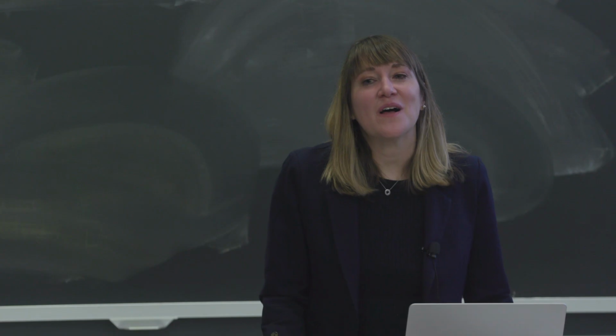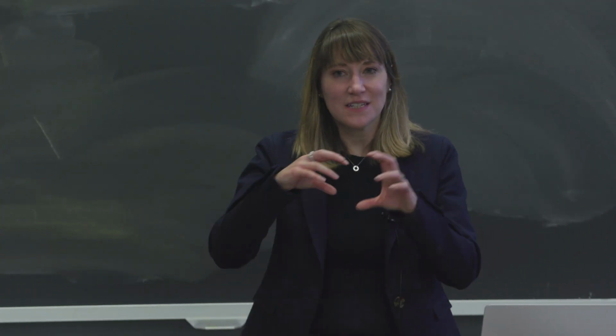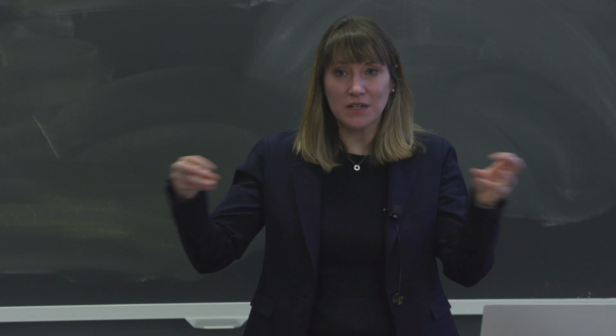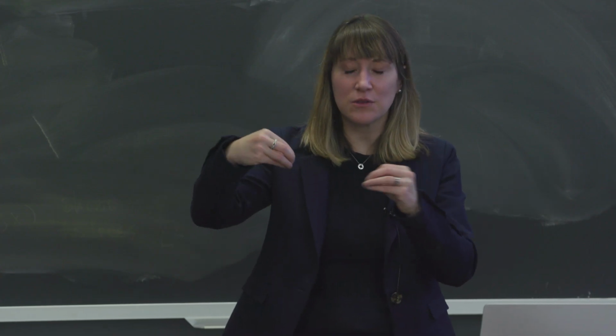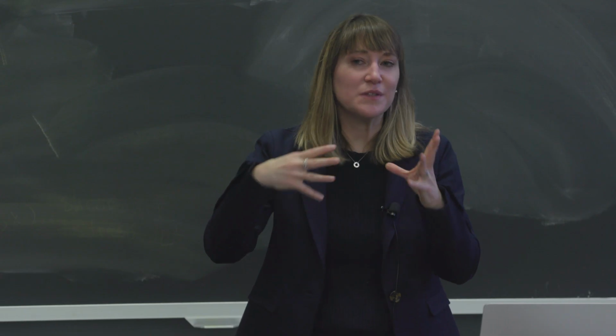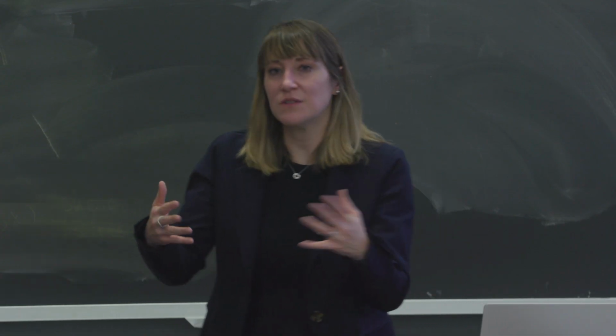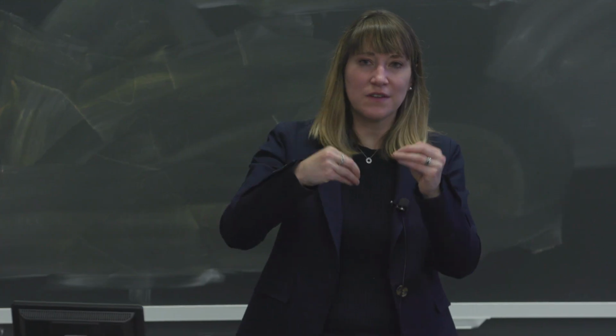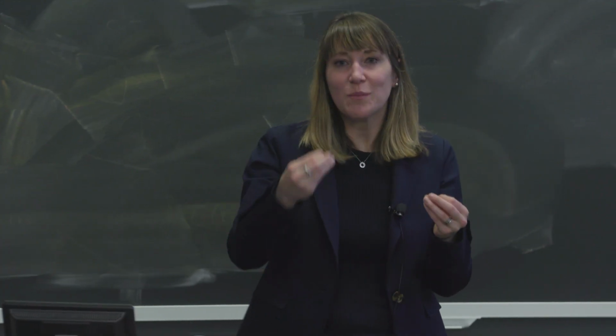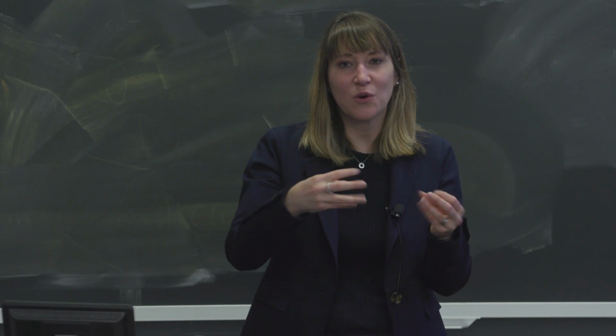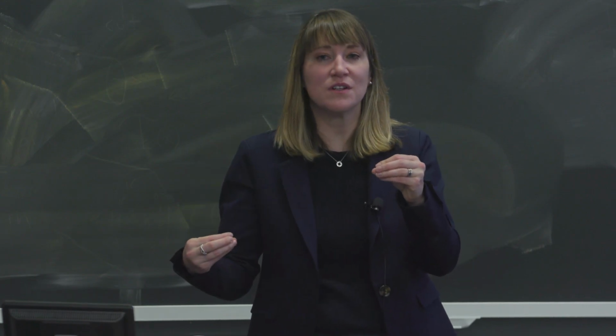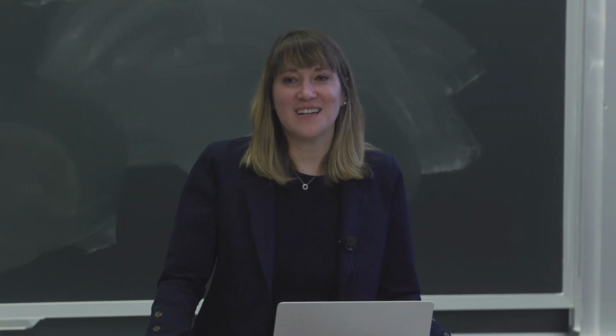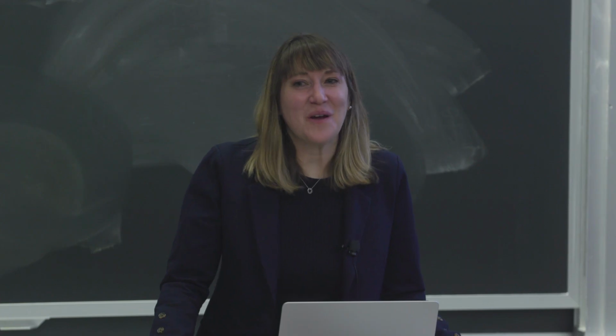Why does it work? I'd love to know. Well, I alluded to the fact that it's important to have an SEI that has a uniform lithium flux through it, meaning we're not focusing our current heterogeneously through certain regions. When you have heterogeneity, it's believed, though I think this is still a working description, that it relates to heterogeneous stripping or plating of lithium. That can lead to overutilization of one area, not enough utilization of another, and then this kind of entrapment process. But I think that's still an open area. It's very hard to just look at the SEI and figure out what it's doing. We wish we could ask it, but it doesn't tell us.